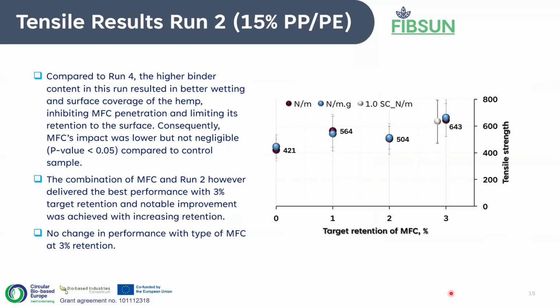So when we check run 2, which is more or less the run with the higher PP/PE bicomponent binder, we see that compared to run 4, we already have an increase in terms of control, as I previously indicated. But in the case of run 2, we see of course that there's an increase with the 1% incorporation, and this was substantial. We found that this increase with 1% incorporation was quite substantial, at least compared to the control.